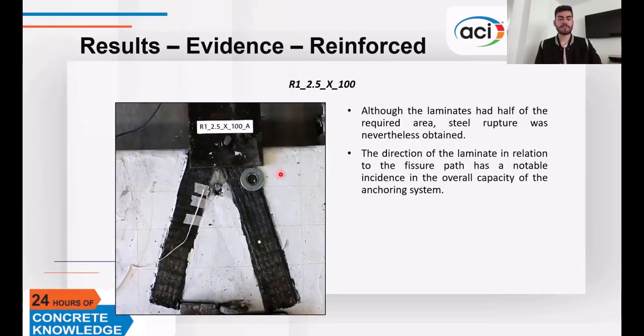And finally, this is half the reinforcement in X configuration. As steel rupture was achieved, we can conclude that the direction of the laminate has a notable incidence in the overall capacity of the system.